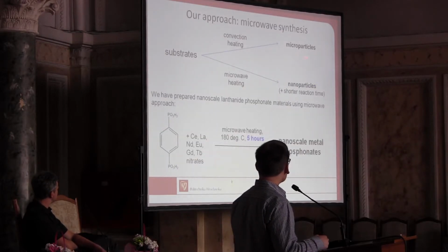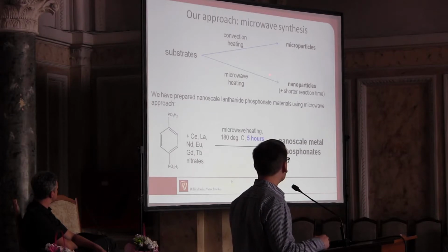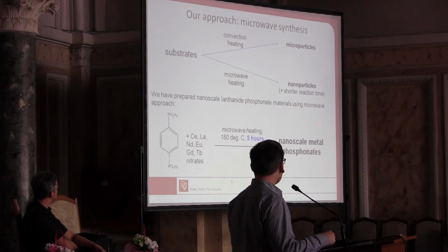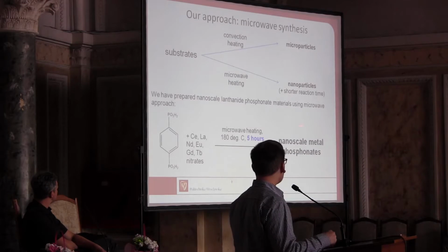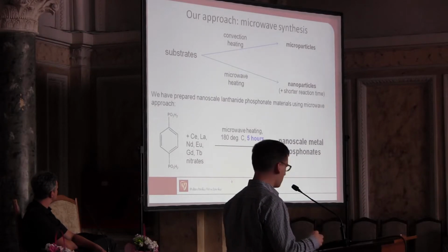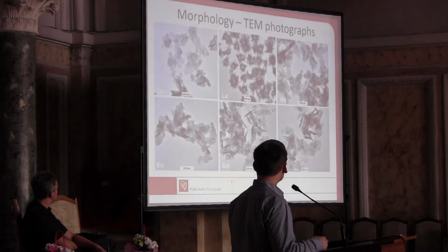Our approach was to replace traditional heating in the convection oven with microwave heating. Microwave heating is known for the fact that the materials obtained in this way are usually smaller. Indeed, we were able to finish the reaction in 5 hours instead of 5 days, and we obtained correspondingly smaller particles. And now I would like to move to the results that we obtained in the field.